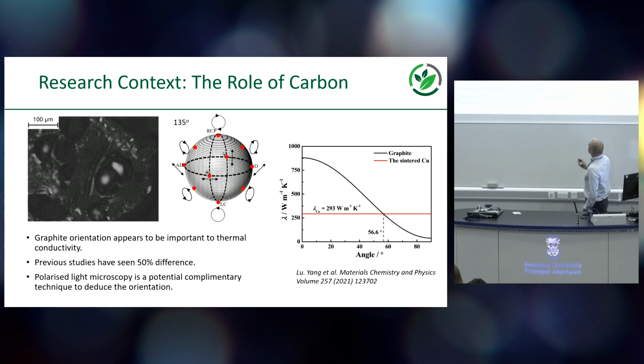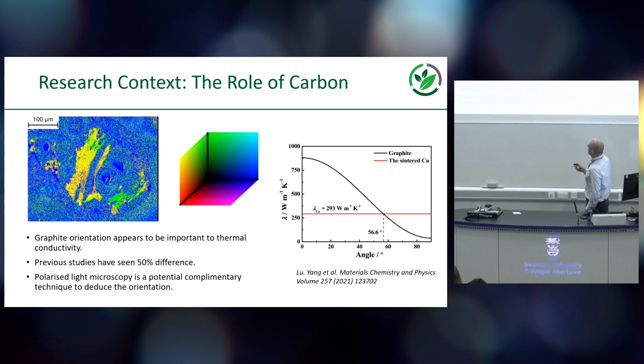And you can actually translate this into what's called a reference sphere that looks something like this, which actually measures how elliptical or otherwise, how skewed the light is or otherwise when it gets back to the detector. And then you can plumb all of that information into a calculation, which then actually tells you what the orientation of the graphite is. And so you can sort of put that against the reference sphere up here. And so there are things that are important for us to clarify and characterize in refractories that have a massive impact on the thermal efficiency of those materials. So this carbon is an important part of the context for our research.